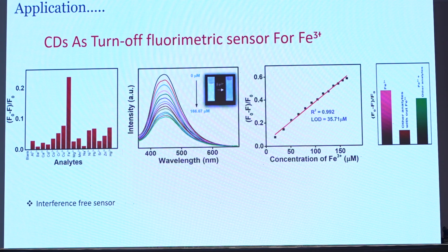The extent of quenching with addition of analytes shows that only ferric ion shows maximum quenching of the carbon dot luminescence. With the addition of ferric ion to the carbon dot, its luminescence is gradually quenched. The relative quenching efficiency shows a linear relationship with the concentration of ferric ion, with a limit of detection of 35.7 micromolar. We have now checked whether our synthesized carbon dot is an interference-free sensor. So we have analyzed relative quenching,